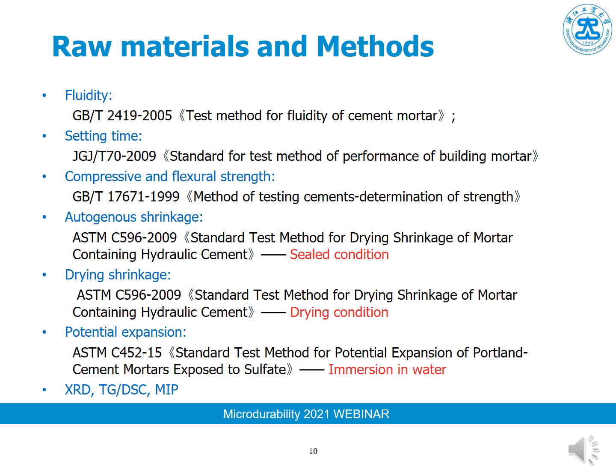We did a lot of tests, which include the fluidity tests, the setting time, the strength, the autogenous shrinkage, drying shrinkage, potential expansion, and we also did some microstructure study, which includes the XRD, TG-DSC, and MIP analysis. For the volume deformation tests, we tested the volume deformation of the mortars under different environmental conditions. For autogenous shrinkage, it was a sealed condition, and for drying shrinkage, it was a drying condition. And for the potential expansion tests, the specimens were immersed in the water, and we tested the length change of the specimens.